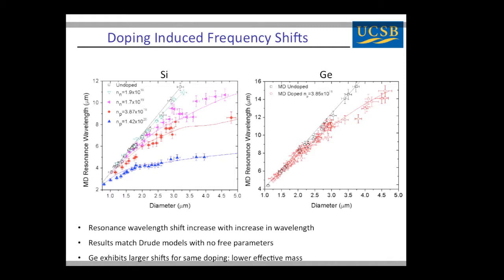And we'll start with the silicon. If you look, there's really a huge difference in the evolution of this magnetic dipole resonant wavelength with size, from an undoped sphere to a heavily doped sphere over here. While we don't yet have access to the phase of the response in this measurement, we can certainly see that we can get very large tuning of the resonance frequency or wavelength with free carriers.